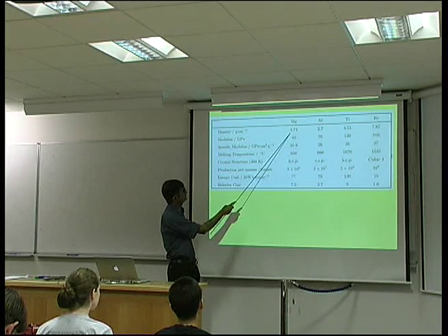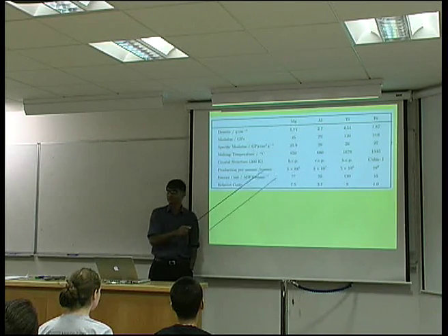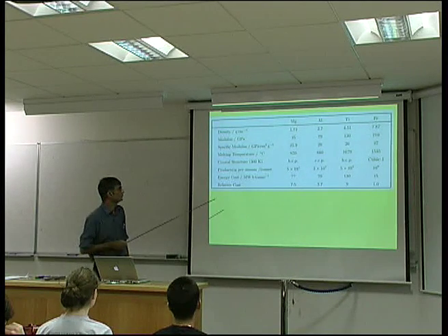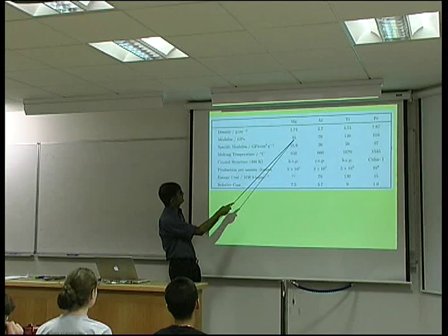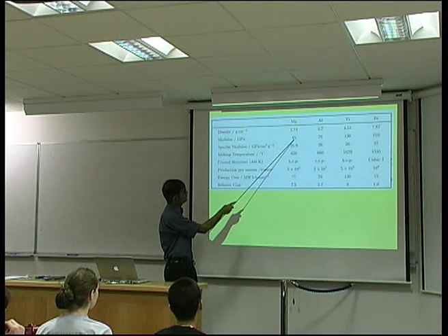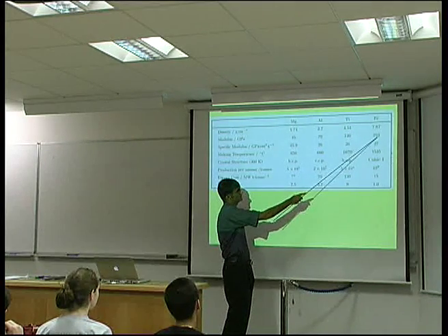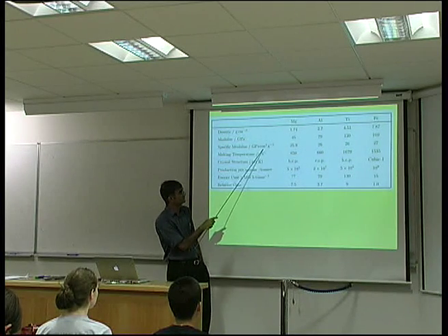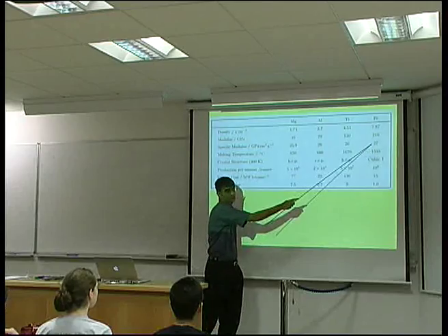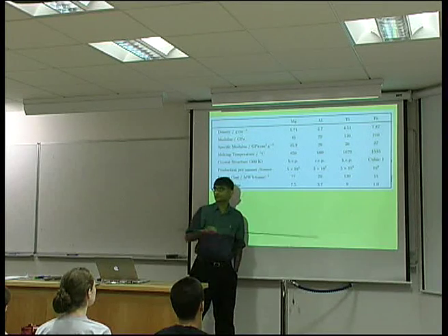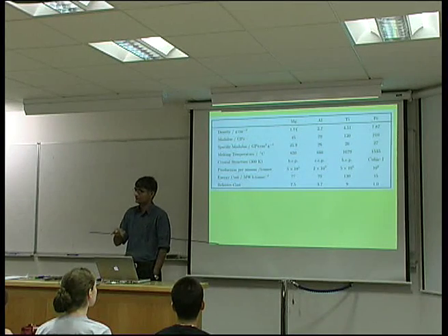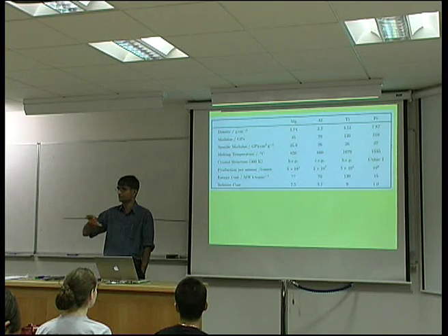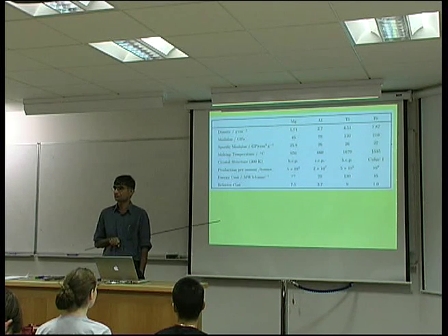Density on its own is not a useful measure. We have to think about properties such as specific strength and specific modulus. So for example, if I take the modulus of magnesium, which is 45 gigapascals, and that of iron, which is 210 gigapascals, and I scale it with density, then you can see that they're more or less the same. Because when we are designing engineering structures, it isn't simply a question of one parameter, but a combination of parameters which gives you a good selection criterion.